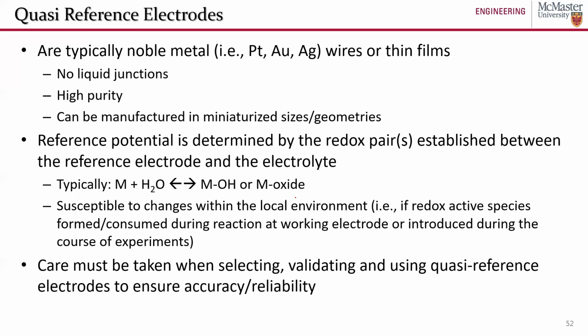But it's important to consider that these are susceptible to changes within the local environment. For example, if your working electrode is generating a bunch of hydrogen and your reference electrode is a quasi-reference electrode of platinum wire, it's going to interact with that hydrogen and form a mixed potential, where the hydrogen-proton redox couple and the platinum hydroxide redox couple have an interplay, and you're going to have a weighted average of those two potentials as your reference electrode potential. So you always want to take care and be sure of what species are being formed near that reference electrode, because that can impact its potential. That's why I say care must be taken when selecting, validating, and utilizing these quasi-reference electrodes.